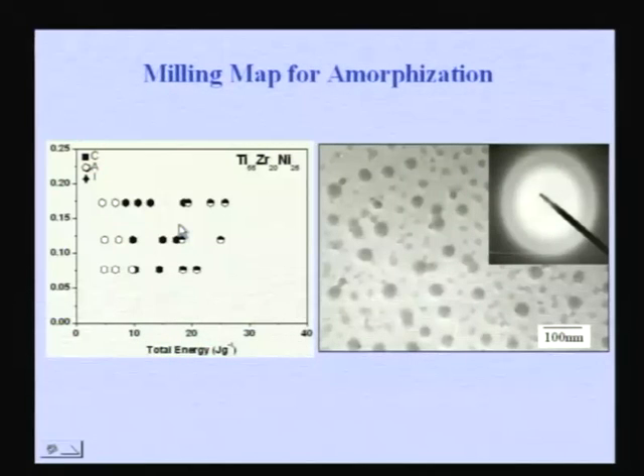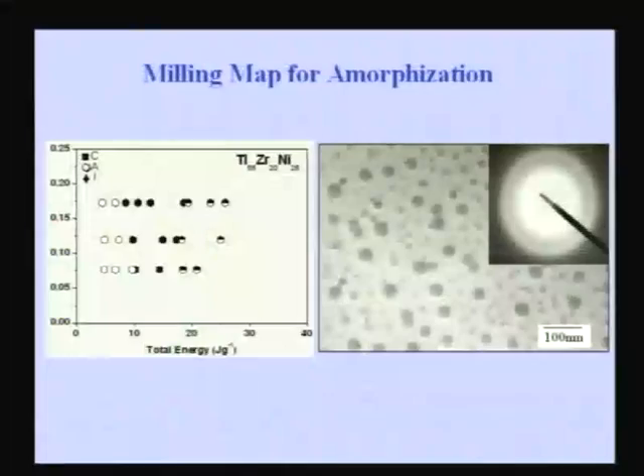If any amorphous phase that forms is not a stable phase, it transforms into a crystal when you heat it, because we know whenever a glass is heated, a glass becomes a crystal. So if you heat this glass, it becomes a crystal. Similarly, when I am putting in more and more energy, more and more defects are coming into the picture, and these defects enhance the diffusivities, and because the diffusivities are so enhanced, crystallization can occur very easily even without increasing the temperature. So the amorphous phase can become a crystal in situ in the ball milling itself without taking it out and heating it in a DSC or doing an annealing. So this is kind of in situ crystallization.